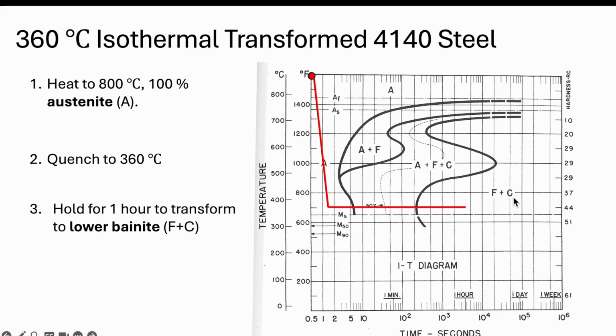And so in this case, like I mentioned before, this lower C shape, this refers to bainite. And so essentially here we have bainite. And specifically, people refer to this as lower bainite because it's the lower range of the C-shape. So that's kind of important here. So lower bainite. And so that's the structure.